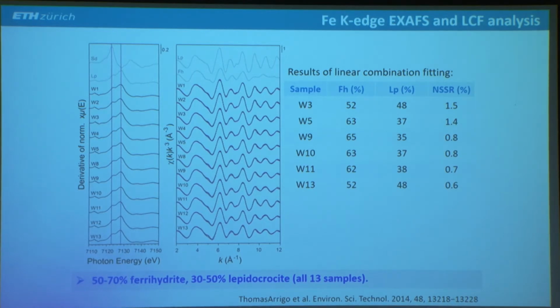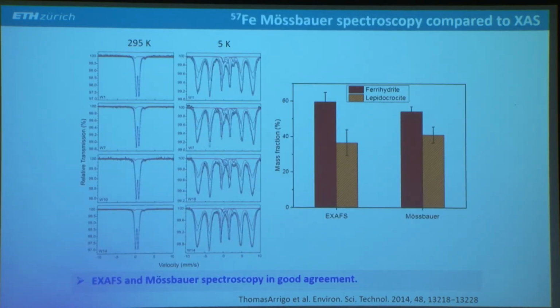And if we do the linear combination fitting, in summary, there was 50 to 70% of the iron bound in ferrihydrite and 30 to 50% in lepidocrocite. Now, interestingly, the lepidocrocite was not detectable with X-ray diffraction. And so we wanted to have another confirmation for that, and we were able to do some Mössbauer spectra together with Andreas Kappler's group in Tübingen.